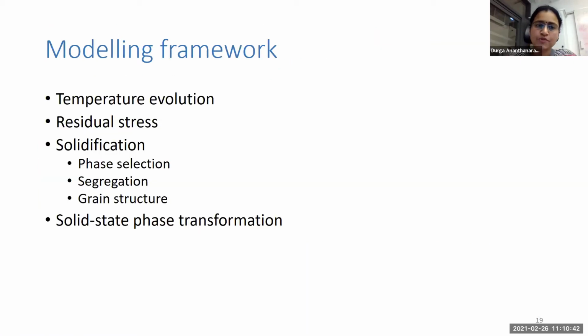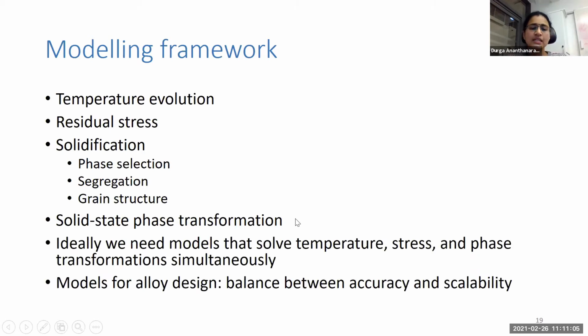So to study these four aspects, how do we go about a modeling approach? We need to look at several aspects. So first, the temperature evolution itself, which will determine all of this, then the residual stress, solidification, which will determine which phases are formed, how they segregate, what grain structure forms, and also solid state phase transformation. And ideally, we would need models that solve the temperature, stress, and the phase transformation simultaneously. But here, the focus, as I said, is on alloy design. So we want to be able to use these models for trying out different compositions and the effect of different process conditions.